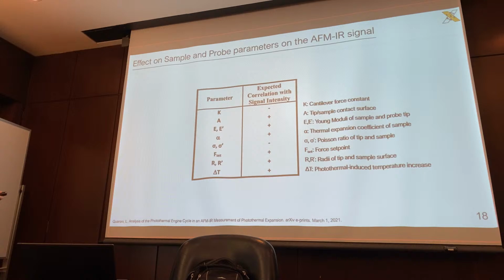In terms of Young's moduli of the probe tip and sample, this one's going to be a little bit challenging to maximize, because you can only increase the Young's modulus of the tip itself so much before you actually begin increasing your cantilever force constant, which balances this modulus out. The thermal expansion coefficient of the sample itself is, of course, going to maximize the signal that you get in terms of a resonant response.